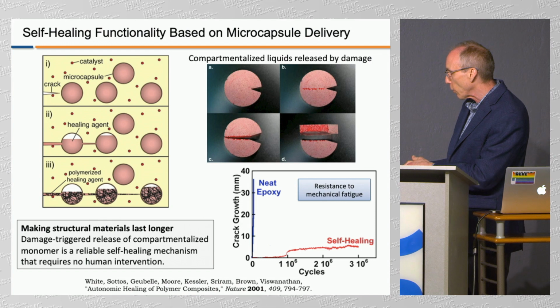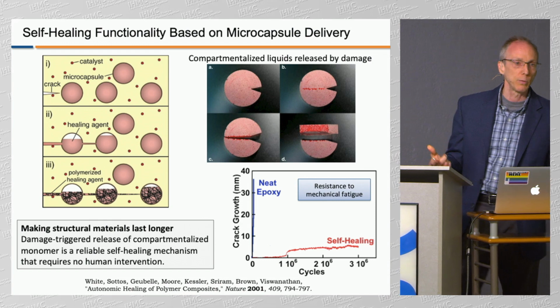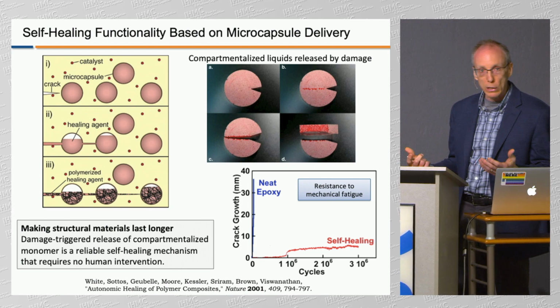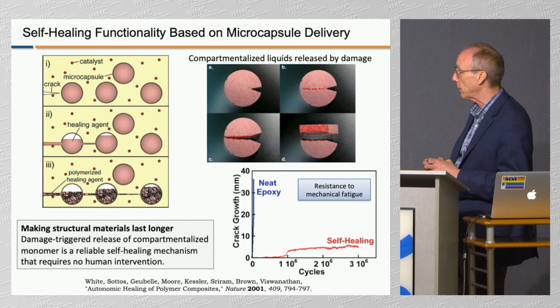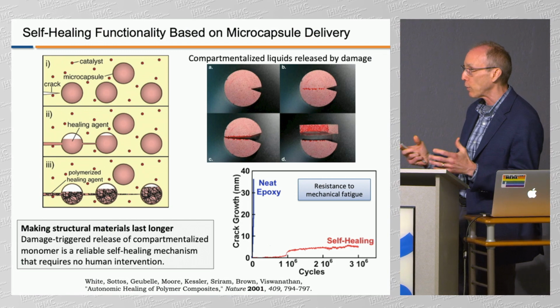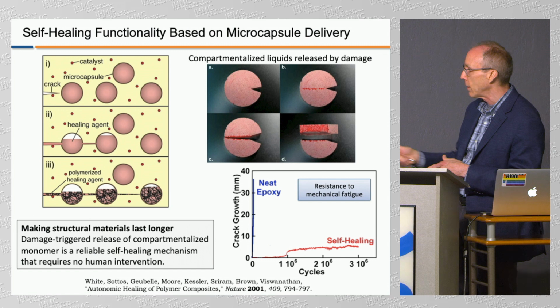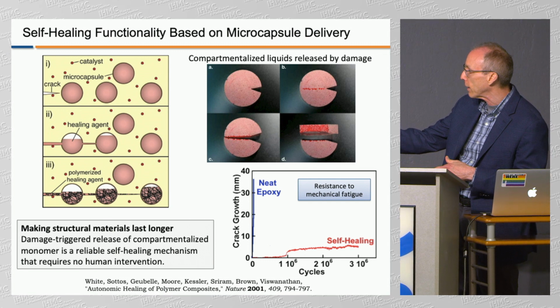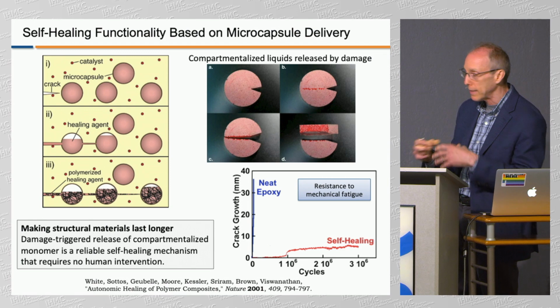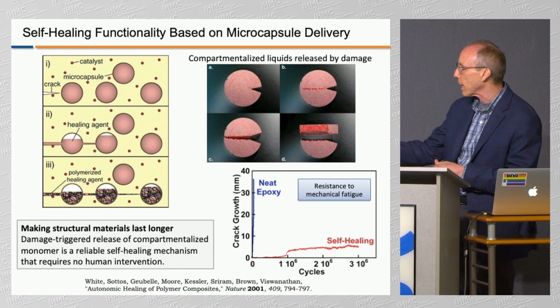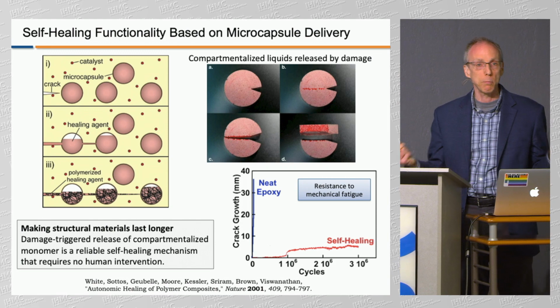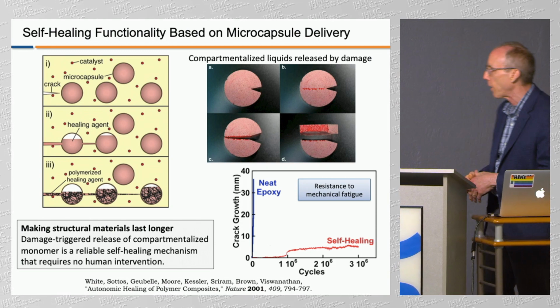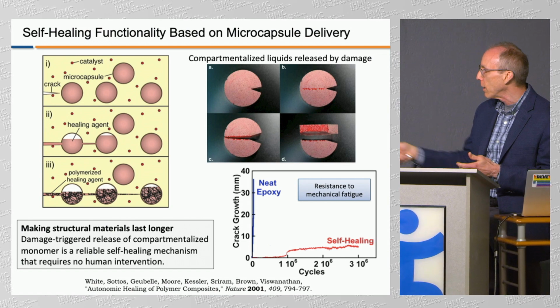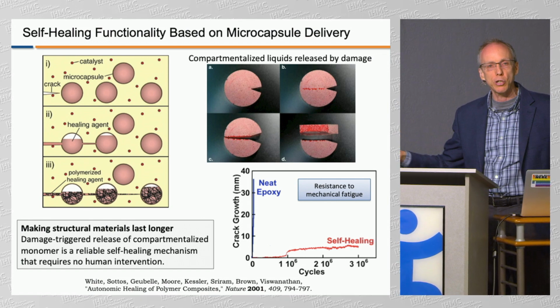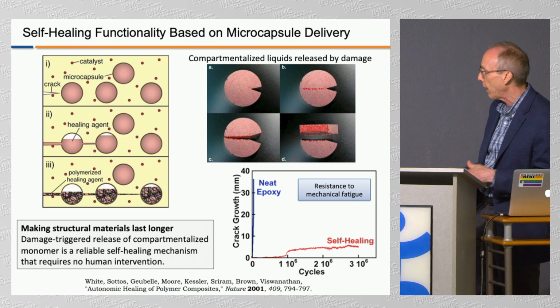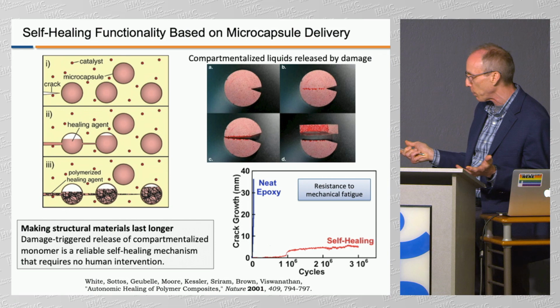You'll notice the year 2001. So this was really the first example of self-healing material based on these microcapsules containing self-healing agents. And in this case, when damage of a crack encounters that microsphere that contains a little bit of liquid, it releases that liquid. That liquid encounters a catalyst, much like GC2, Grubbs Catalyst 2, and then causes a polymerization to take place. There's voids left behind, but the main thing is the large area damage has been filled and repaired, and that's what this plot is all about.